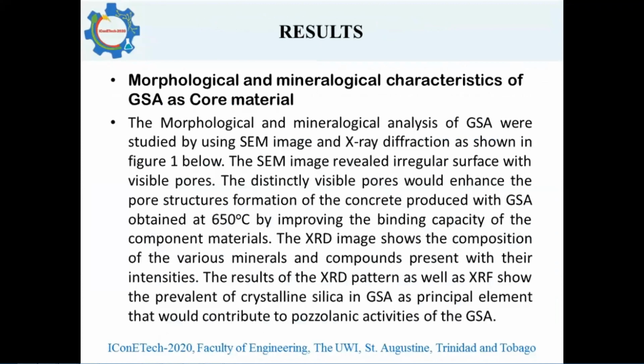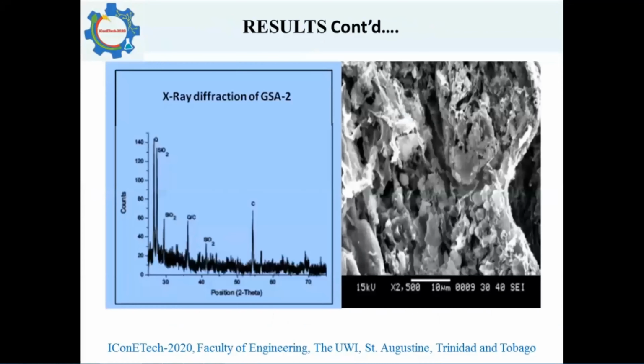So, results and analysis. The morphological and mineralogical characteristics of GSA as a core material show, after studying the SEM image and the X-ray diffraction as shown in the figure below, that the SEM image reveals an irregular surface with visible pores. The visible pores will enhance the pore structure formation of concrete produced with GSA obtained at 650 degrees Celsius by improving the binding capacity of the components. So this is the SEM image of the Groundnut Shell Ash.